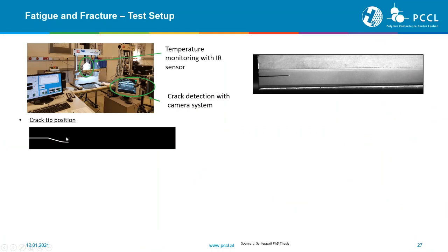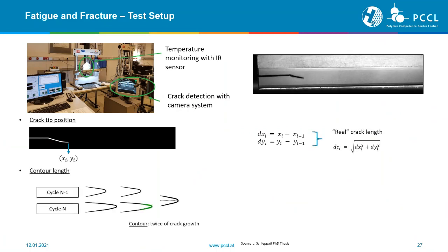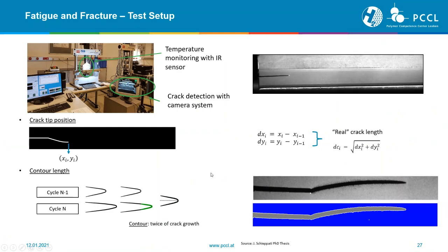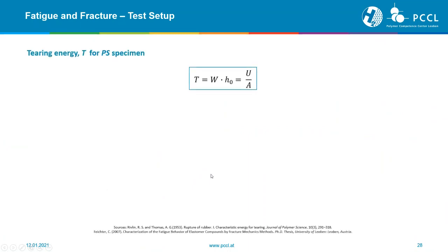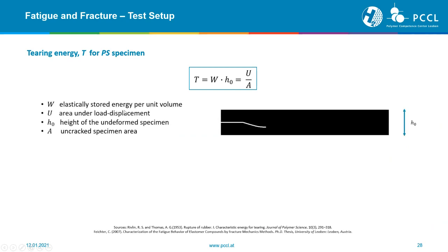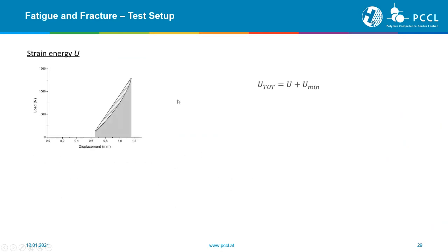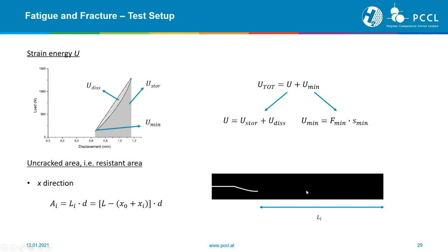We developed a method where we can measure directly with this camera the crack tip position, X, Y, and then finally end up with the contour length to calculate fracture mechanic parameters. These fracture mechanic parameters, in this case, we've chosen the tearing energy for pure shear specimens. The important thing for us is, on one hand, the hysteresis, which means the area under the load-displacement curve. And on the other hand, the uncracked specimen area. Therefore, we need the position of the crack, with some boundaries, ending up with the definition of the strain energy, as I mentioned. So we have the total energy, with dissipated and stored energy. We defined in our case a minimum energy, and then end up with this uncracked specimen area, as I mentioned before.